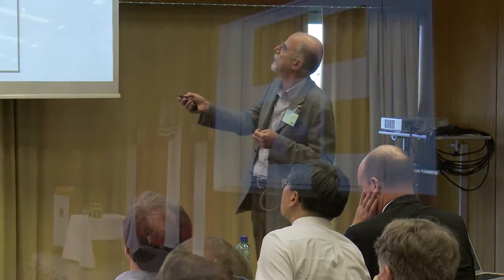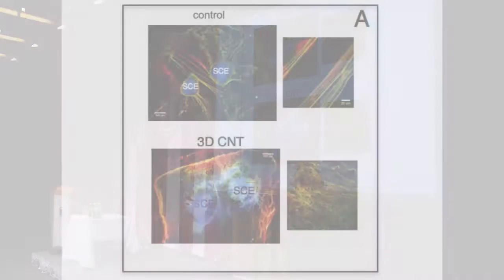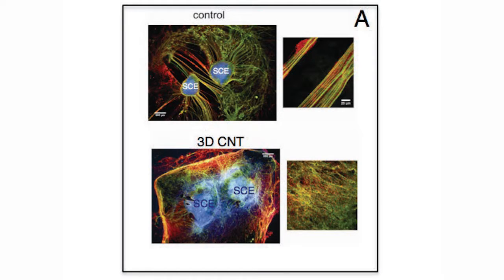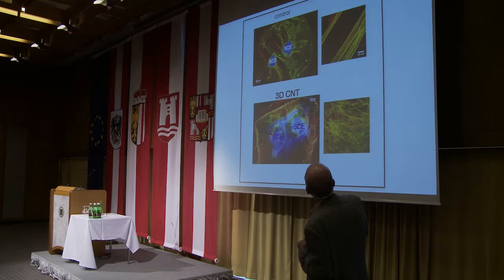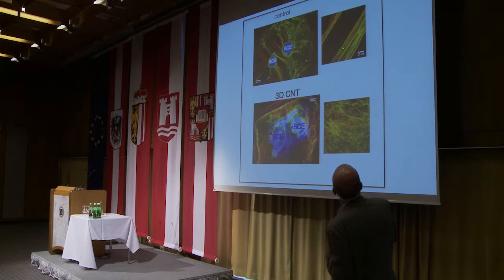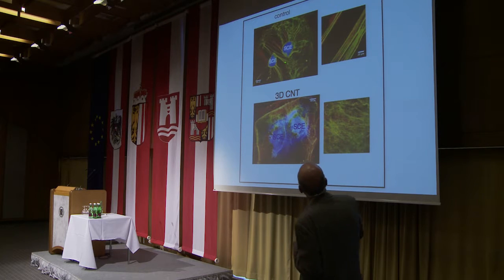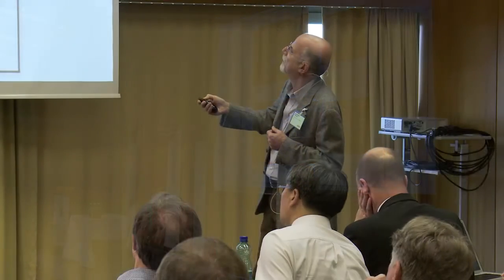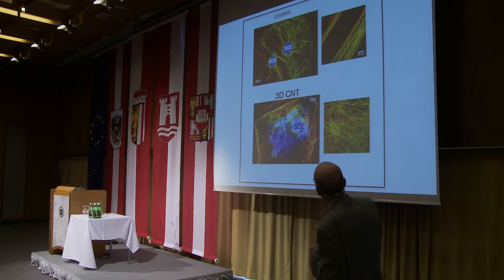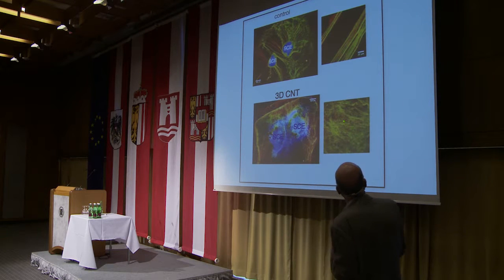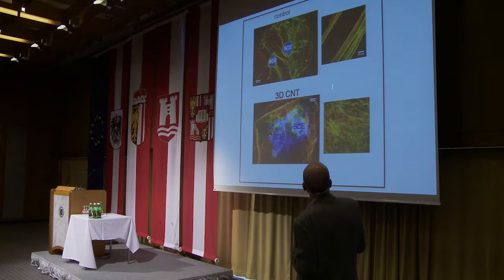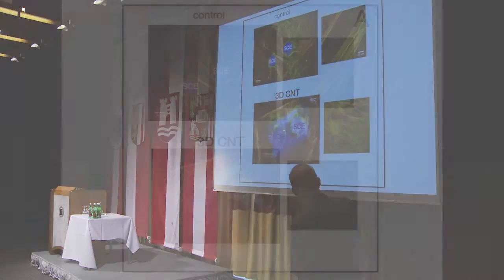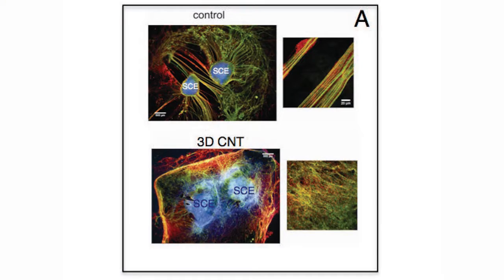Well, first of all, the morphology. We have the two slices. These are spinal cord explants. The two slices on the control. You can see that between the two slices, there is no really tight contact. The fibers grow. The fibers are very thick in diameter, very strong, but they don't try to go towards the other one. When we place the two spinal cord explants on carbon nanotubes, on the 3D sponge, we can see that here all the fibers grow much thinner than here, but that between the two slices we have a very thick layer of carbon nanotubes.